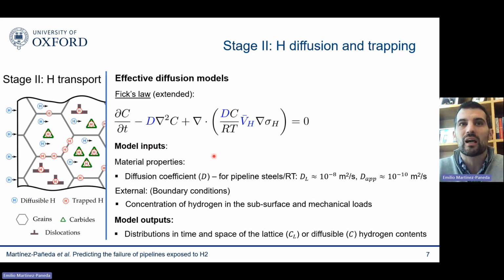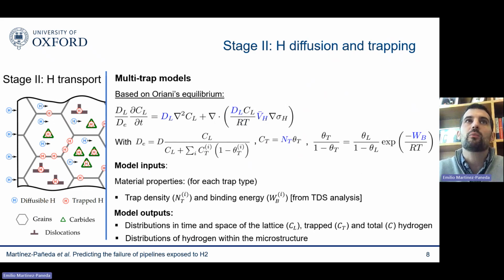Well, we get a distribution in time and space of the lattice or diffusible hydrogen contents. And then you have another model, which is a multi-trap model, which, for example, you could do based on Oriani, or you could do based on McNabb-Foster. This is what you see based on Oriani. This is a situation where you're resolving the hydrogen distribution within the microstructural defects.